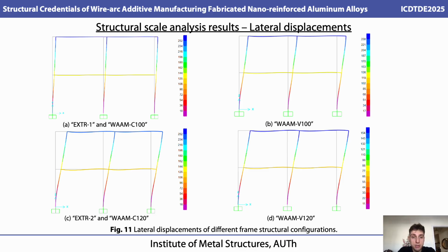These are the results of the structural scale analysis in terms of lateral displacements. The seismic combination leads to the most critical lateral displacements. As you can see, for the first sections, the material improvement, the nano treatment, led to no reduction in the lateral displacements as initially expected, because we do not have greater stiffness. We only have larger yield stresses. But when we're using the variable thickness sections, we get decreased lateral displacements, and the corresponding drift ratios are decreased.